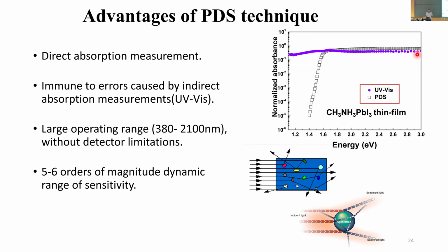So what you see here is I have a film, which is a perovskite film. If you don't know, just consider it as a film, and it has its own absorption spectrum. That's in purple, which you measured using a traditional spectrometer. And what you see here is the data is plotted on a log scale, usually plotted on a linear scale because you don't have much sensitivity, so you only measure the linear.